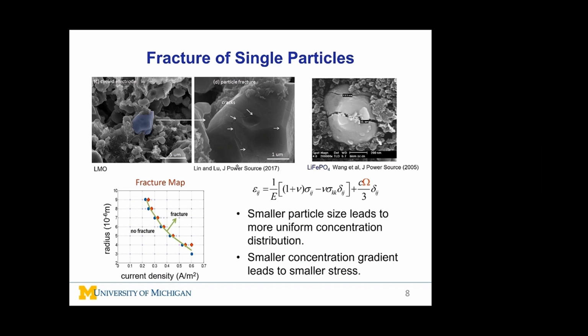Studies have shown that smaller particle size leads to more uniform concentration distribution. Smaller concentration gradient leads to smaller stress. This figure shows that for a given charge-discharge current density, when the particle radius is small enough, no fracture occurs.